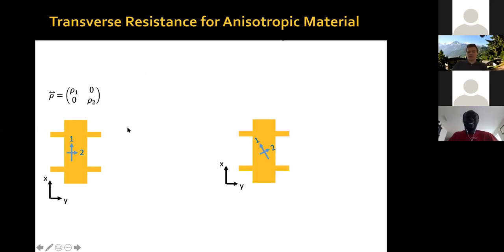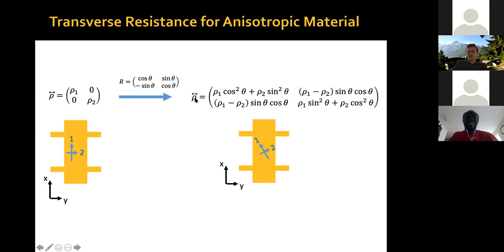However, if you have a device where your device axes are at some angle with respect to your anisotropy axes, if there's a rotation angle between the two, you need to do a transformation of your resistivity tensor, and the experimentally measured values of your resistivity are actually given by these formulas. So as long as you have different resistivities along the one direction and along the two directions, you have a finite transverse resistance measurement in your Hall bar, okay? Given also that the angle is not 0 or 90 degrees.